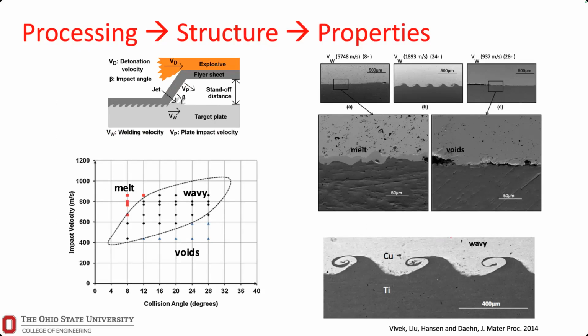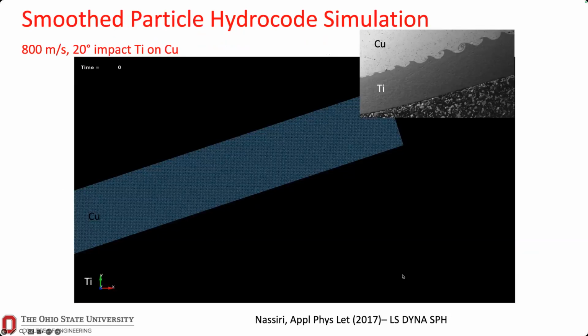And what we're interested in, the material science paradigm, is go from processing to structure to properties. Our process in this case is an explosive-like impact-driven process. We control the metal speed, we control this impact angle. We have a number of ways of doing this. This would be kind of a whole different talk, but we have gotten very good at using capacitor bank discharge, lasers, chemical augmentation, other methods of getting materials moving very, very fast, and we can do some very interesting things with metal forming that way. The important part of this is we can control the impact velocity and collision angle. There's a wide window there where we can get very good dissimilar metal welds. We know how these work very nicely.